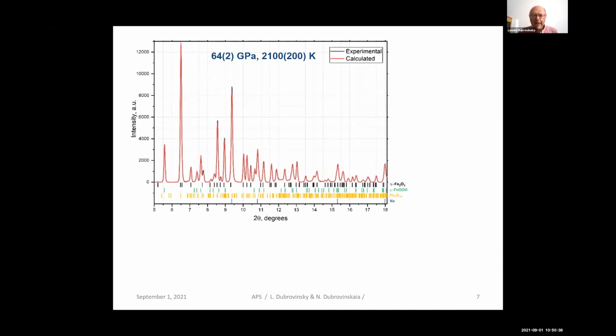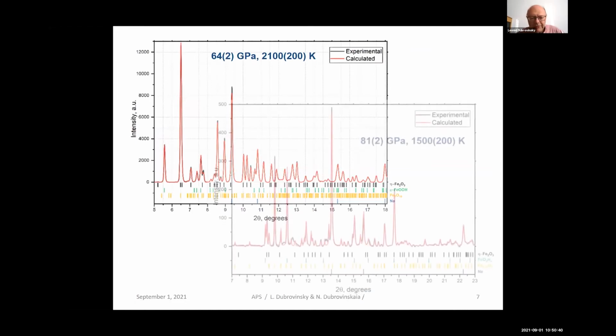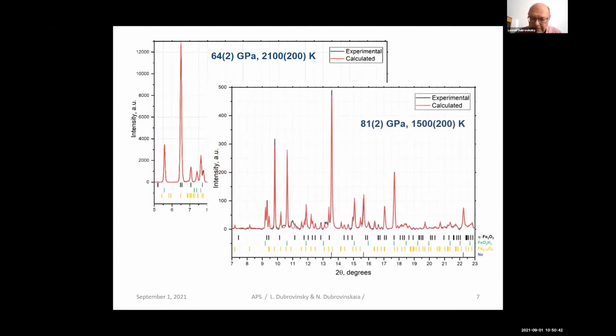So we will use in our discussion further the data which we obtained for these two model slabs. Now, here are a couple of powder diffraction patterns collected at 13-ID-D at APS. And you can clearly see that the patterns are nice, but believe me, the interpretation of these patterns just based on the observed reflections would be impossible if you don't know the phases and if you do not know the composition.